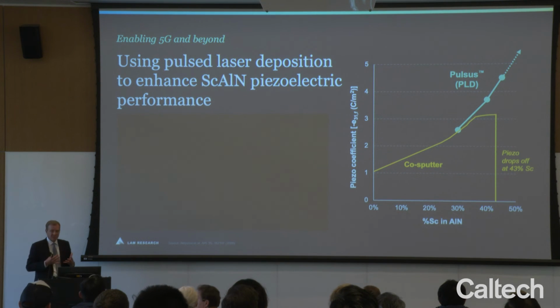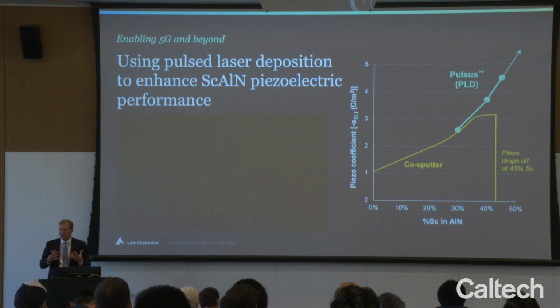the traditional deposition techniques that have been used for many years to build these types of devices are things like PVD co-sputtering, where you simultaneously try to sputter two different targets. And if you can get those targets to sputter in the right ratio, they'll form a film on the wafer that gives you the characteristics you want.